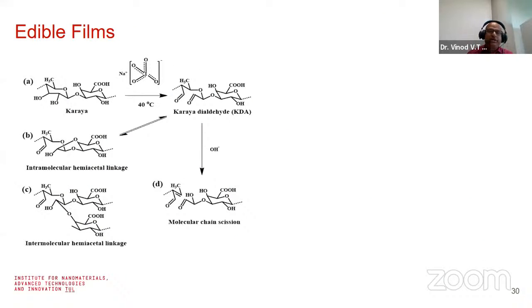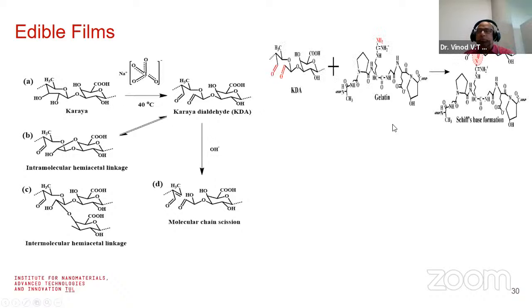And another important research we developed was making edible films out of these gums. We used Karaya gum and periodate treatment, and we made a Karaya dialdehyde material, and this Karaya dialdehyde we have reacted with gelatin to form gelatin-based tree gum composites. So this material is used as an edible film.